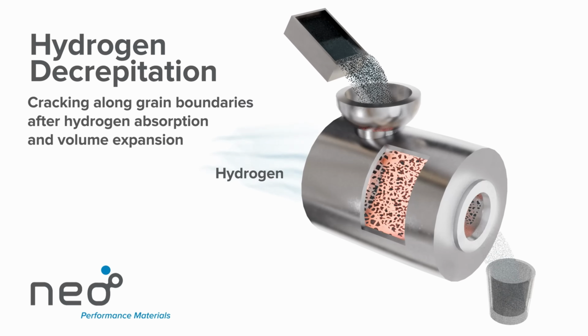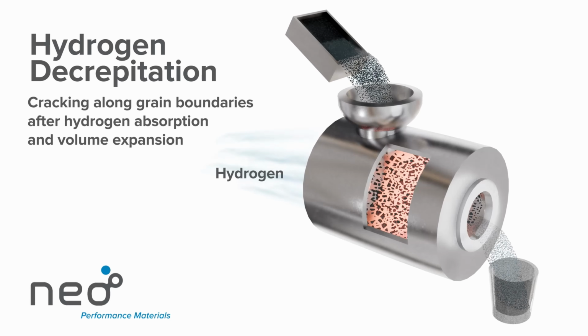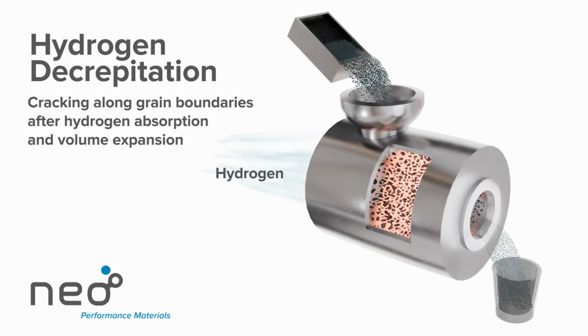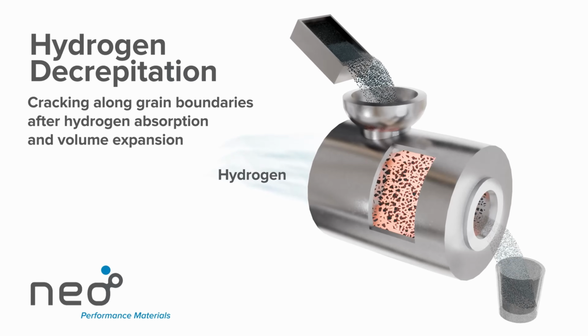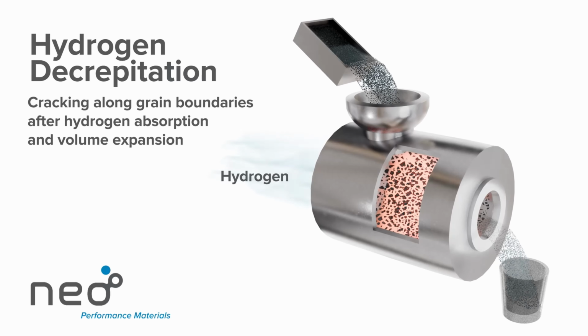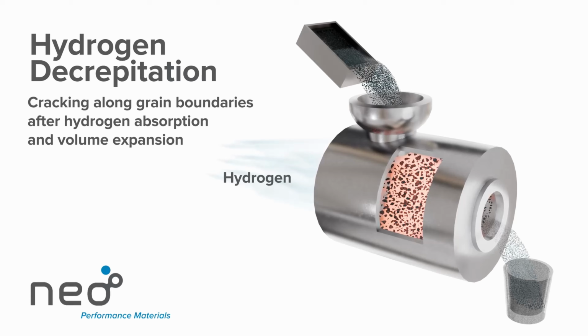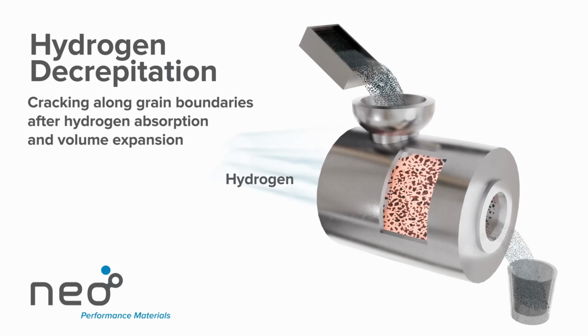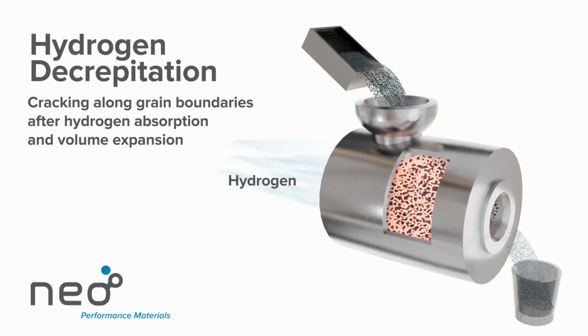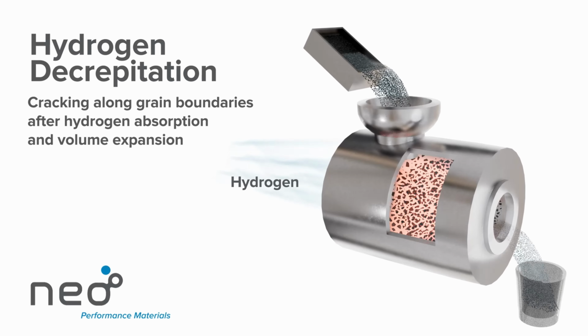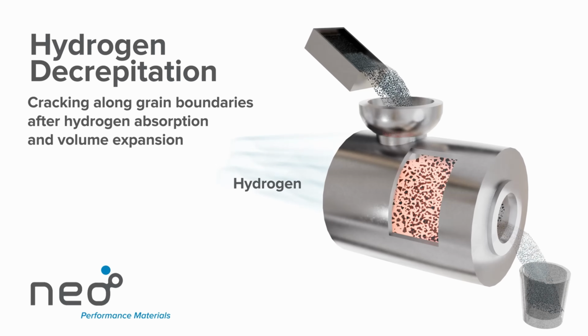The strip-cast flakes absorb hydrogen gas to form two different hydride phases. The different volume expansions of the two phases result in cracking and embrittlement of the alloy microstructure. From this point onwards until the magnet block coming out of the sintering furnace, the material does not come in contact with oxygen. Everything takes place in vacuum.